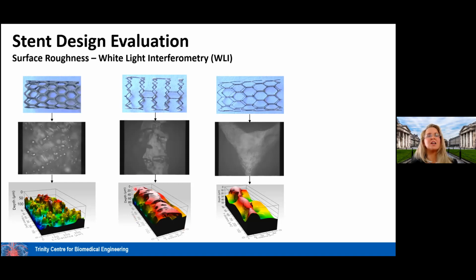Here we can see once we etched for a period of time to remove the struts, which again reduced the strut thickness somewhat, but wasn't as long as for the simple honeycomb etched, we do get improved surface finish, but we could probably etch for a little bit longer to improve that again.